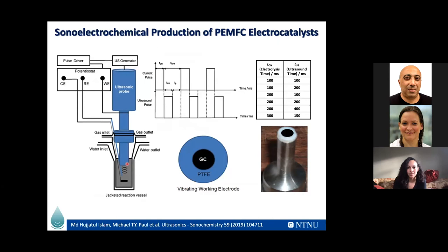So everything was earthed. We really had a working electrode linked up to the substrate, and we also had a reference electrode away from the field, and a counter electrode, which was actually platinum, or it could be another reference counter electrode. But by playing with the galvanostatic pulse and the ultrasonic pulse, you could play also on the size. Okay, so a few milliseconds of current, where we know you get your nanoparticle formation or your platinum formation, then a blast of ultrasound to dislodge these nanoparticles from the surface.